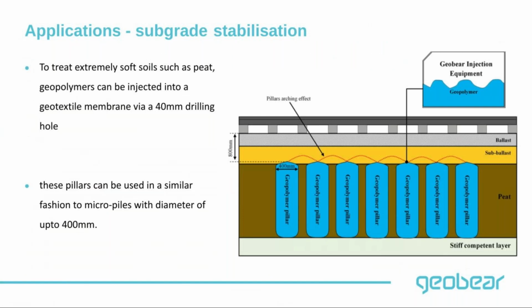Another technology we have is using the geopolymer to create a pile-like structure. We have these specially designed geotextile sacks that we can inject the geopolymer into, and the geopolymer fills the geotextile sack and creates a pile-like structure with a diameter of almost 400 mm. That's much wider than what you normally get from conventional micropiling. As a result, we get a much higher arching effect than with conventional micropiling, and a much better load transfer.